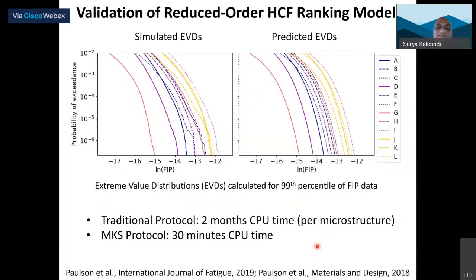You can do the same with fatigue. Now we can evaluate microstructures for fatigue. In fatigue, one looks at fatigue indicator parameters, or distributions of FIPs. As you go higher, it's more likely to fatigue. As you go this way, it's less likely to fatigue. These are all different microstructures. If you are using physics-based models, you would use crystal plasticity models to compute them, and each simulation takes a very, very long time. These are much faster on a relative basis. You can see the comparison, and the ranking is about the same. Of course, there are some differences, but the ranking is roughly the same, and the fit is pretty good.